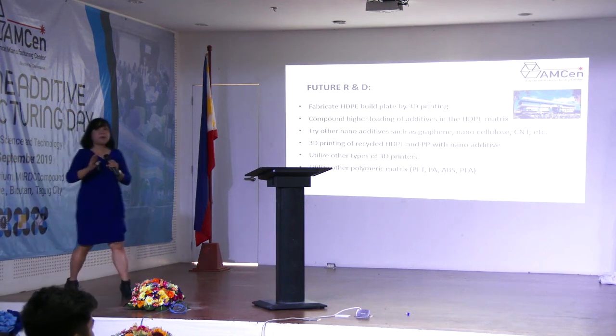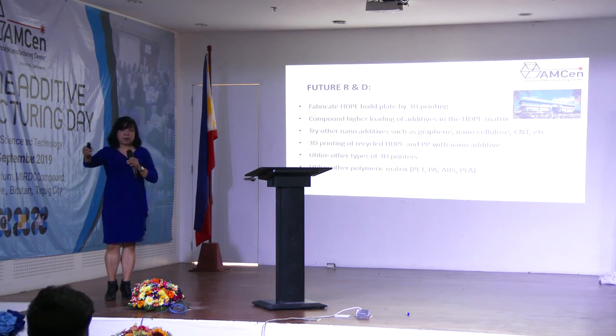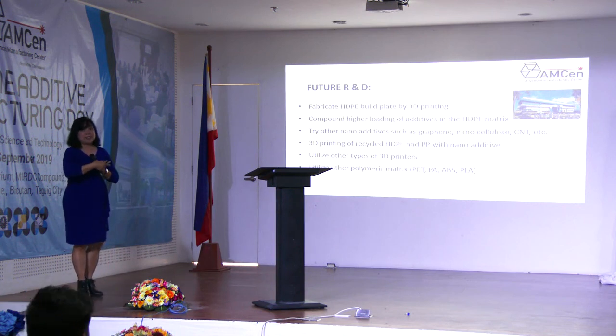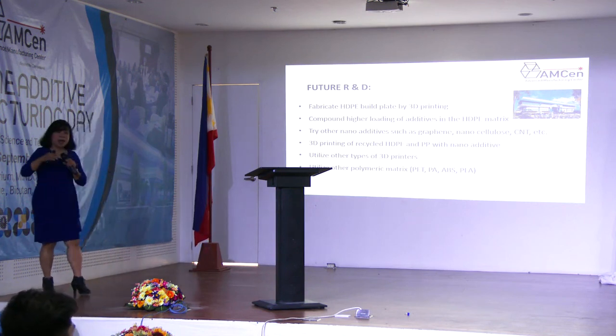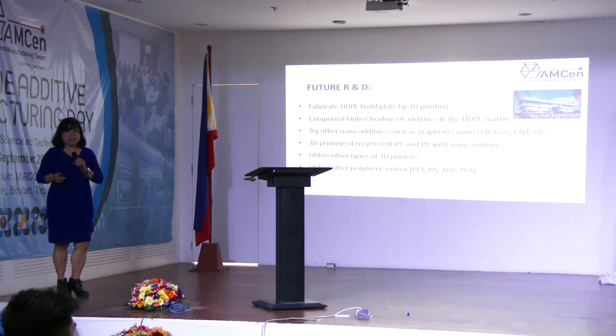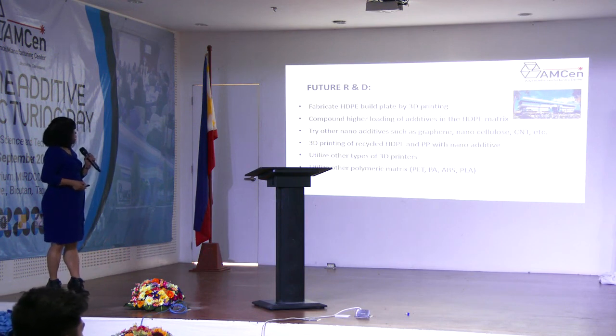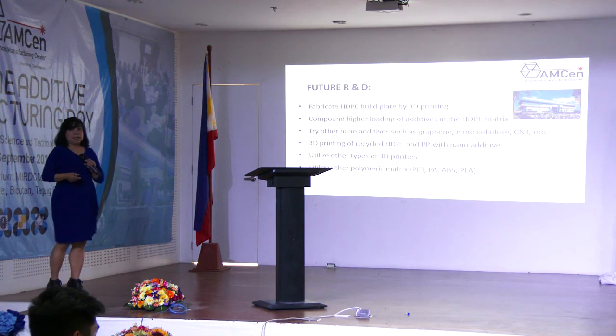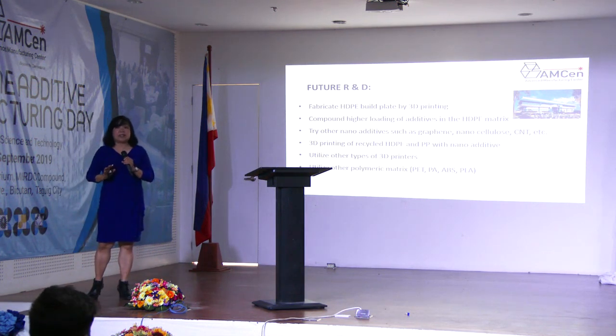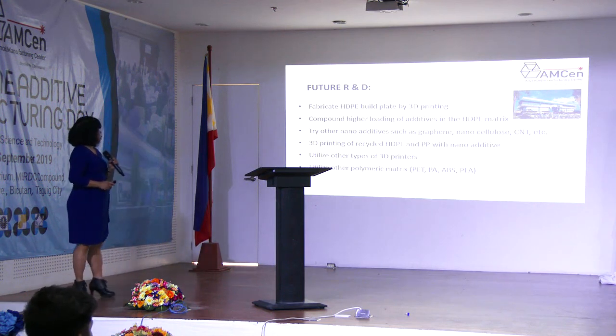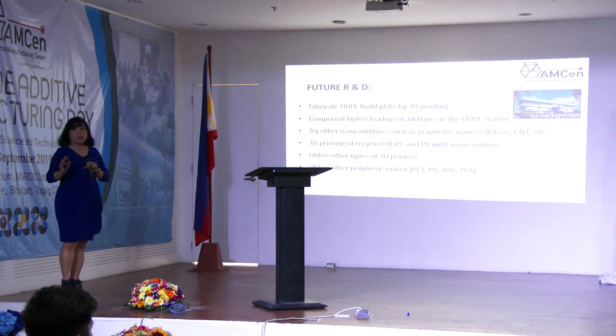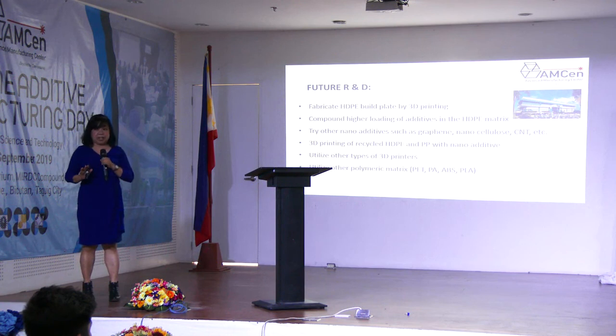We can also try fabricating an HDPE build plate and try to roughen the surface of the same material, HDPE, and then try to print. But there is still a challenge here on how to remove the specimen from the build plate because it is the same material. But we could try this experiment, and also we could try higher loading of the additive. And you could try also using other nano additives. And also we could try using recycled HDPE or polypropylene with nano additive. And also we could try printing using other formats of 3D printing.